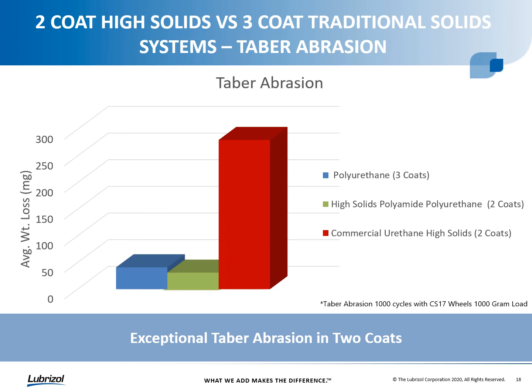And so we see that we have pretty comparable performance in just a 2-coat application with the high solids material compared to the 3-coat system, and significantly higher performance when compared against the commercial urethane high solid system applied in 2 coats, where it has upwards of over 250 milligrams of weight loss, so significantly poorer abrasion resistance compared to the polyamide technology.